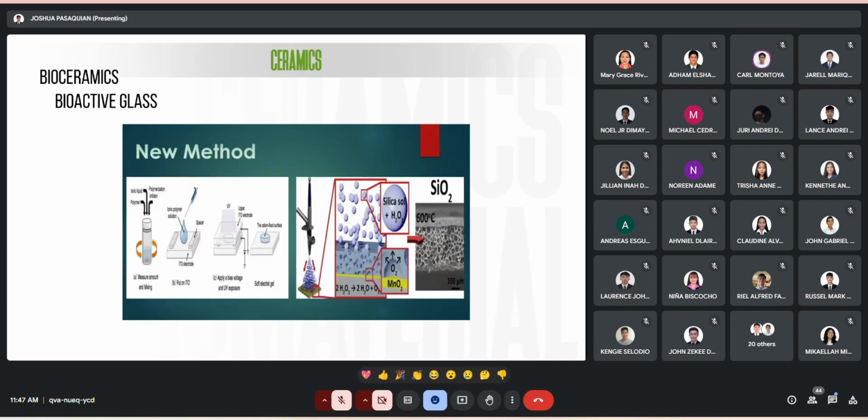A newer technique was developed, and it's based around the sol-gel foaming process by treating the contents of bioactive glass to various processes like hydrolysis and condensation reactions, followed by low temperature treatments. This formed sol-gel, when exposed to fluids in the oral environment like saliva, undergoes ion dissolution, which is essential